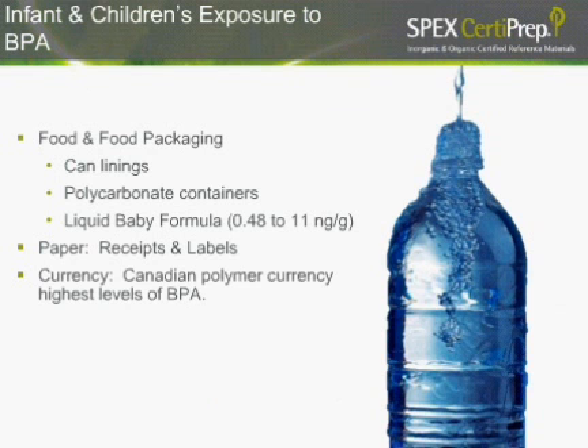Another surprising source of bisphenol A exposure, which I only just read about within the last few weeks, is currency. There was a study done showing that bisphenol A was found to be on most of the world currencies, with the highest suspect being the Canadian polymer, the new Polymer currency. These had the highest levels of bisphenol A. And a lot of the suggestion was that the currency, whether it be the paper or the Polymer currency, was having a transfer of bisphenol A from the receipts that we keep with our money or in our wallet or our purses, that the powder from the receipt was actually starting to settle on the currency.